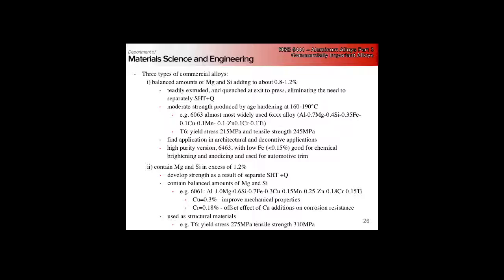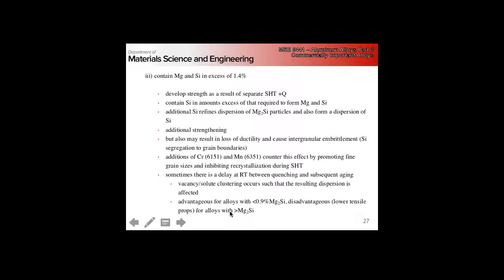If we raise the alloy content, we get a slightly higher strength, but the trade-off is we have to do a separate solution heat treat and quench—we don't use it directly in the as-extruded state. Magnesium and silicon are still kept balanced, and the most important alloy here is 6061, the bicycle frame alloy, used as a structural material.